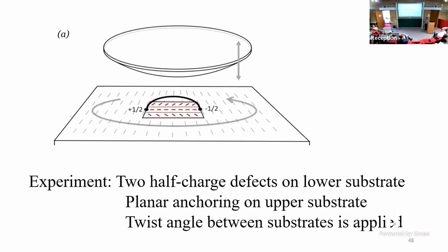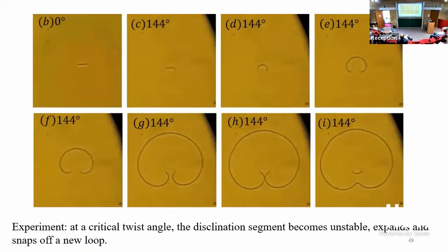They didn't actually do a superposition of a plus one half and a minus one half defect. They did this by rubbing. So they just made three little rubbing directions. So most of the sample has planar anchoring along one axis. Then they have these three little domains, but there's really a plus one half defect and a minus one half. So plus one half, and there's a little arch, and then the top is planar and they rotate it, one with respect to the other. Okay, and again, here are these shapes.